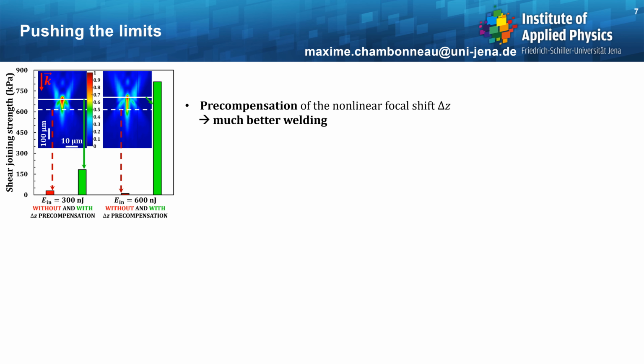Alright, so now that we know the value of delta Z for different input pulse energies, we can come back to our initial welding problem. Especially, we can precompensate the position of the focusing objective lens during the welding by delta Z at the desired input pulse energy. And the results are essentially shown here in terms of shear joining strength for two different input pulse energies, without in red and with in green delta Z precompensation. And what one can conclude from this figure is that precompensating the nonlinear focal shift leads to a much better welding.